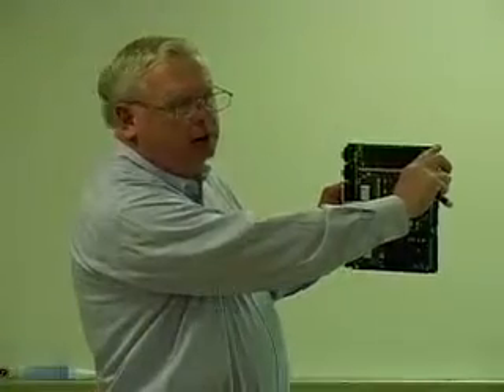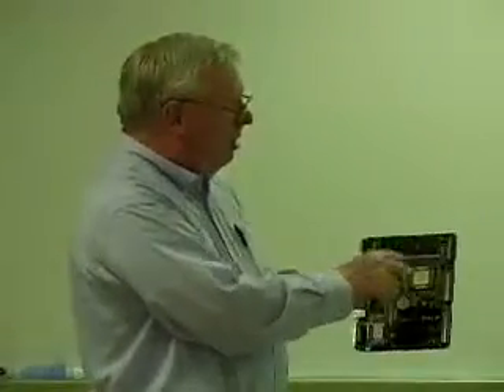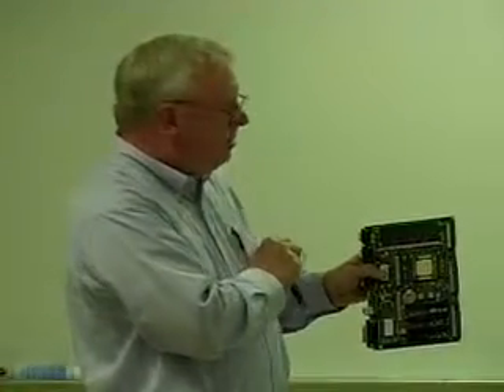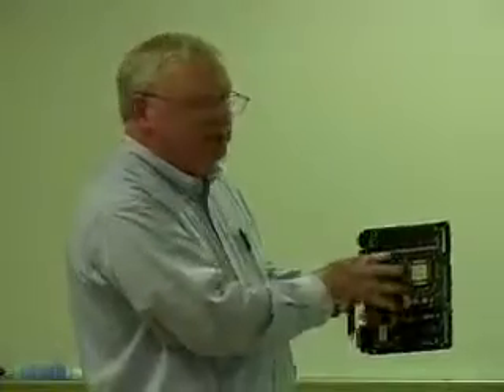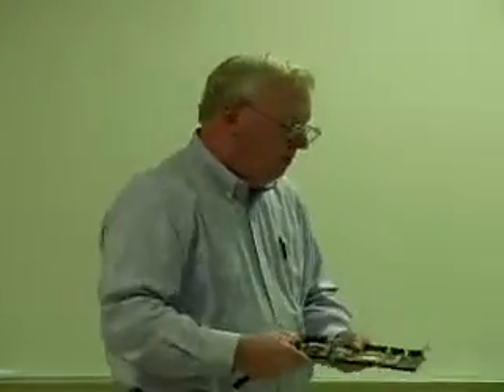Now, where this has really caused problems is if you have a board, and let's say in this part of the board we had a bunch of BGAs where there's a lot of thermal mass, and down here we didn't. This part of the board will not get anywhere near as hot as it should. There's a mismatch in thermal masses, and therefore when this reflows through the furnace, if you're not careful, you will not get good solder attachment with the BGAs. Now, there have been companies, and I will not name them, that have said, oh, we can fix this by raising the reflow temperature. Let's change it to 270 or 280. Well, there are probably components that cannot take that, and we've seen problems like that. So that's why it becomes very important to know something about the thermal masses on your board.